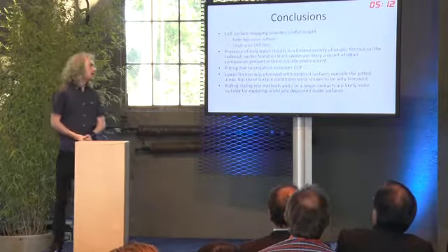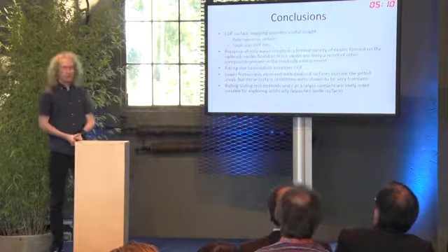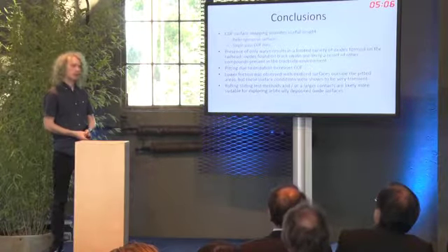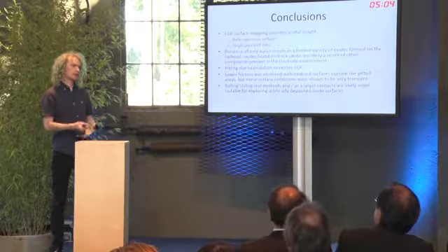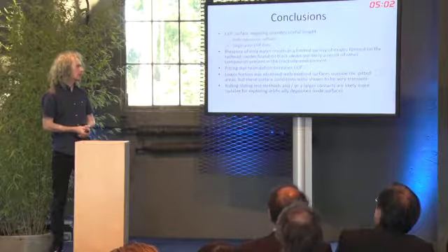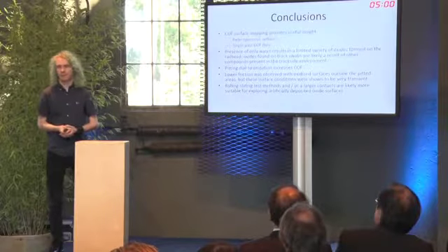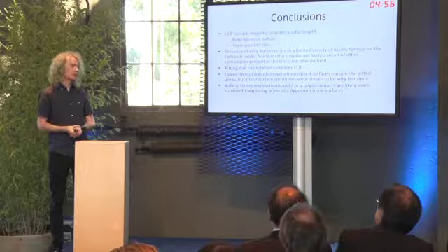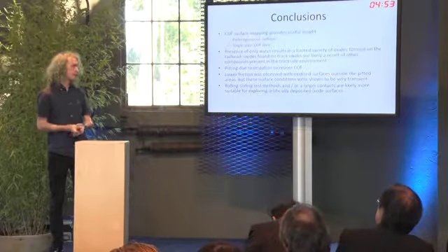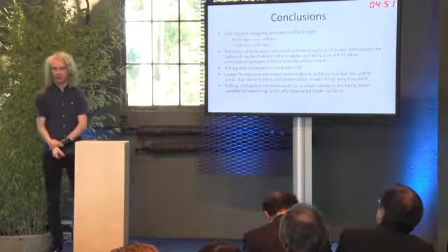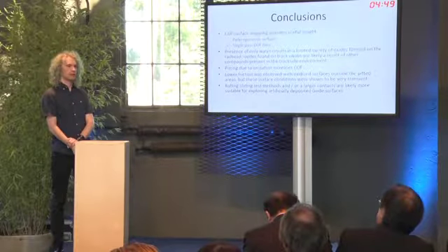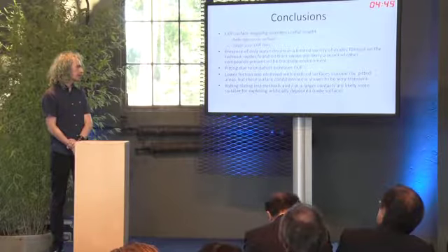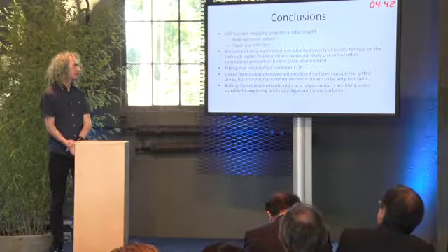From our XRD, comparing the swabs to the ones that we've synthesized in the labs, we found that there's a huge difference between the amount of oxides that we've been able to synthesize, because our conditions were incredibly controlled, we only used distilled water. In the presence of only water, we found that it produces quite a limited amount of oxides, predominantly lepidocrocite.